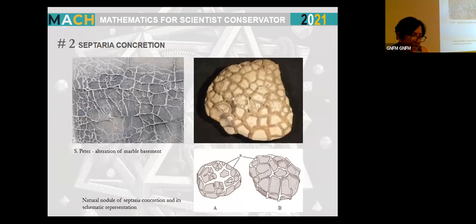Okay, in the geological field, the degradation morphology closest to ours is represented by the septarian concretion. These are nodules characterized by cracks filled with calcite that indicate a contraction of the inner material, probably occurred during the degradation phase. Cracks vary widely in shapes and configuration and may include extensive networks of shrinkage cracks, lenticular, vertical, or radial, and sometimes concentrically oriented. Many concretions exhibit multiple cracking events.